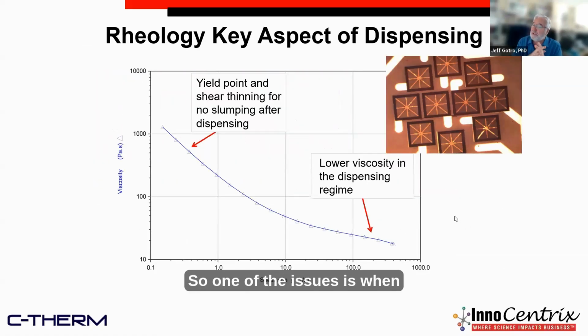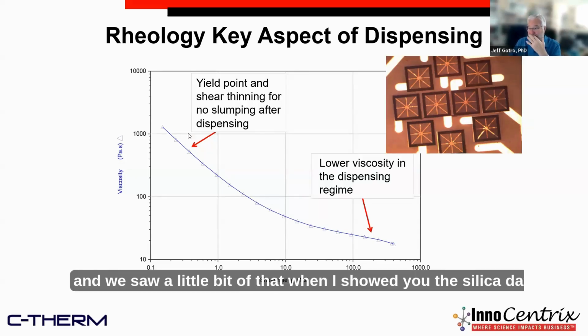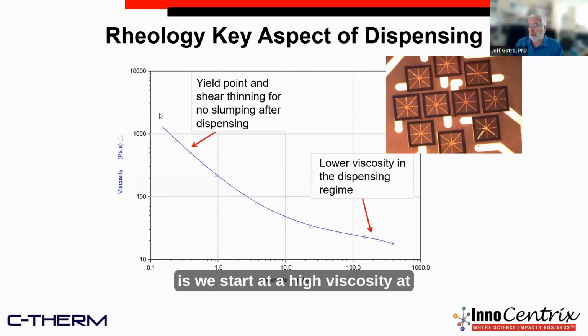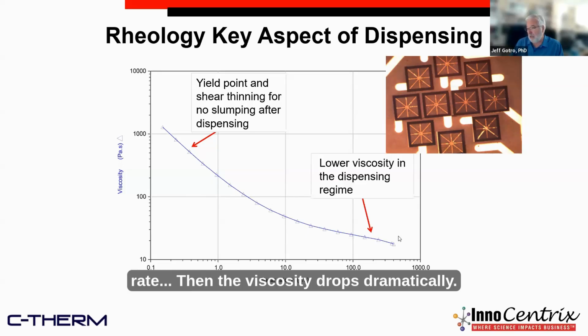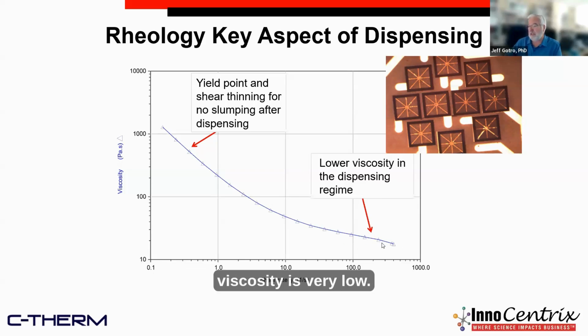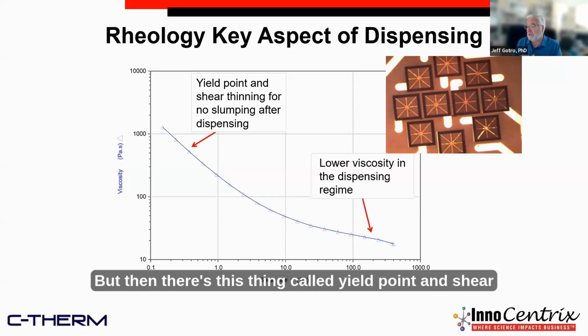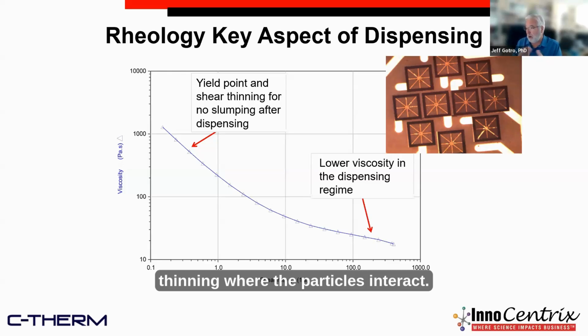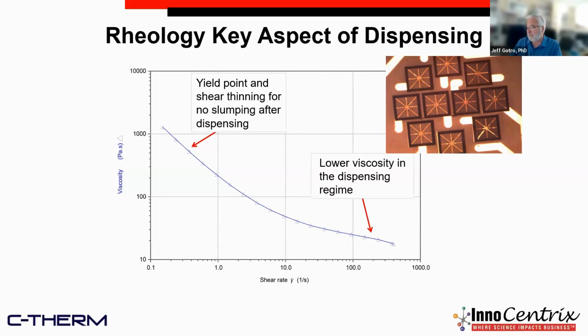One of the issues when we dispense is we have this curve, and we saw a little bit of that when I showed you the silica data. We start at a high viscosity at a very low shear rate, and then as we increase the shear rate, the viscosity drops dramatically. So we dispense out here in this high shear rate range where the viscosity is very low. But then there's this thing called yield point and shear thinning where the particles interact.